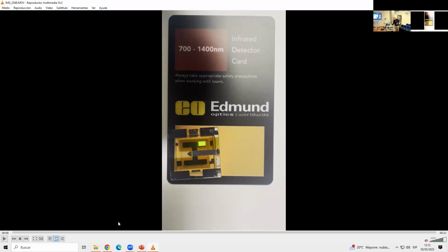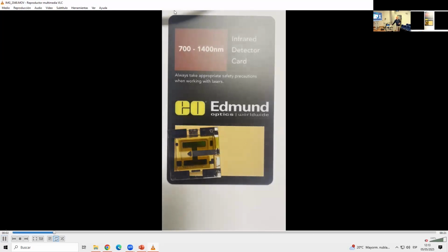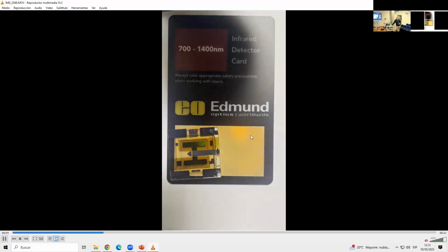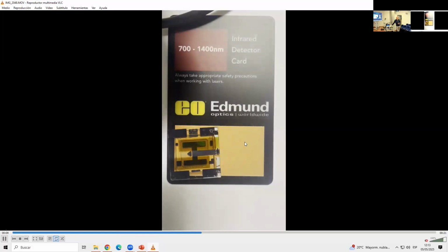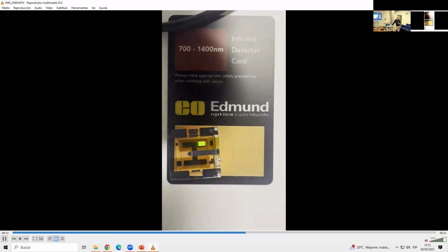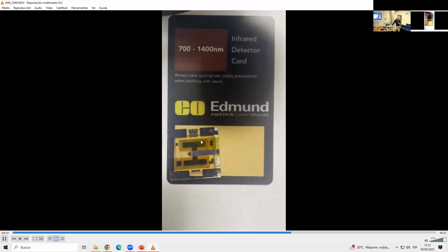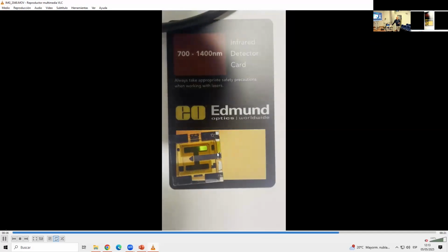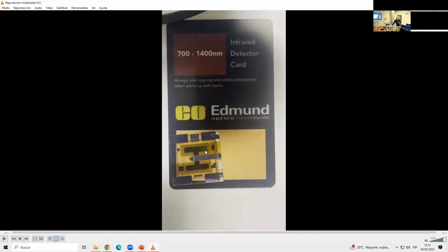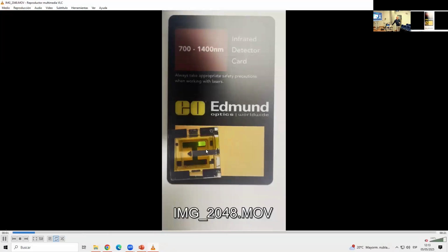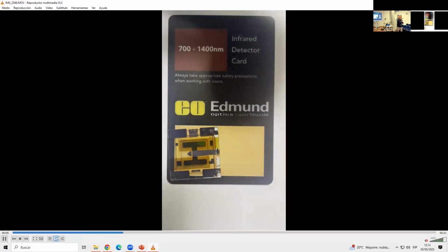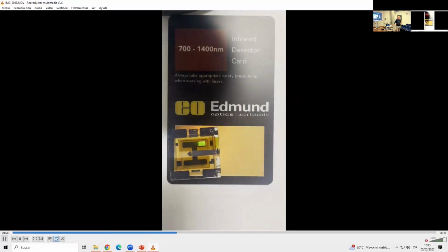And if I can get this to start. So we do shine, and then you have to believe me, we shine infrared light on this. You see a little yellow spot here where the infrared detector card detects the infrared, but you see that pixel here, you have to look here where the mouse is, that stack of 35 layers. It's about a 4% efficient up conversion at these low light intensities, because we are pretty good at making high efficiency detectors, and OLEDs are very efficient at light emitting.